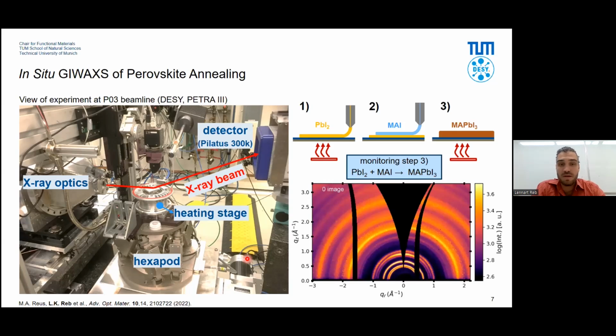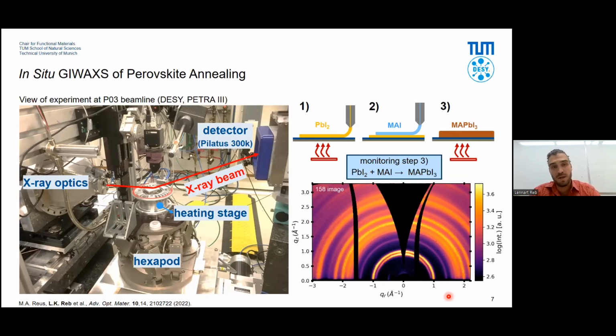So this is how a GIWAXS pattern looks like, and this is image 0, so this is when starting. And now I'm going to show you a video of how it evolves. And as you can see, there are things changing. Some inner rings disappeared and some other rings got stronger. And after that, okay, it seems to be kind of stable. So what we have here at this q value of 1 is the perovskite ring, this bright ring here. Slightly inside of that, we have lead iodide, and further inside, we have solvent-perovskite complexes. I'm going to show you the video again, and you can see how these complexes vanish and the perovskite ring gets stronger and grows. So there we can in situ follow the disintegration of these solvent complexes and the formation